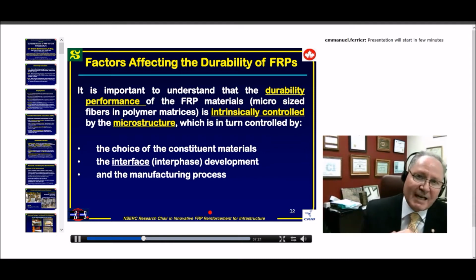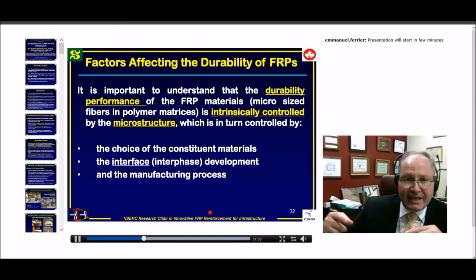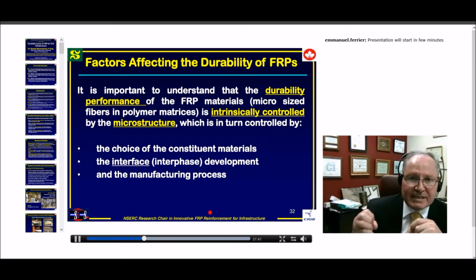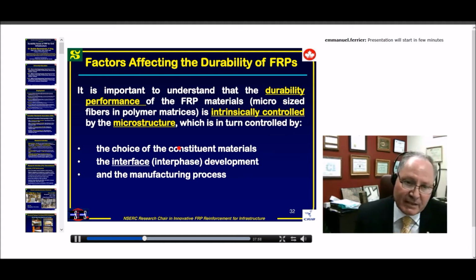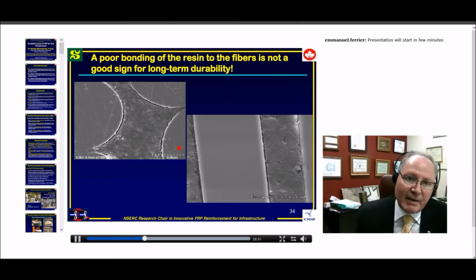Sometimes, but this is for the external surface, you have to add sand, or make grooves or something like that after you make the smooth bars. But when you are using pultrusion with open die, of course, you have access to the rebar during the manufacturing process, and you can add helical fibers, or you can do any external deformation, before the polymerization of the resin. But as you have access, it means it is in contact with the atmosphere, so you can have some pores and something like that. So the thing is to have well-distributed pores, as I will show you later. So this is really extremely important.